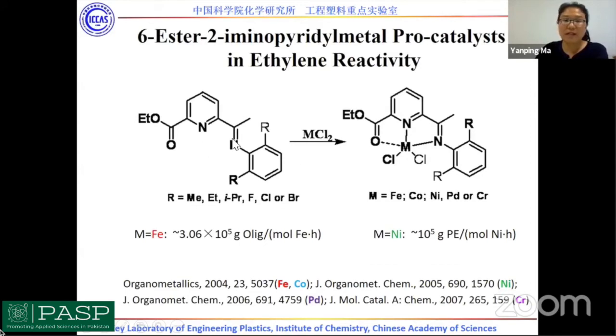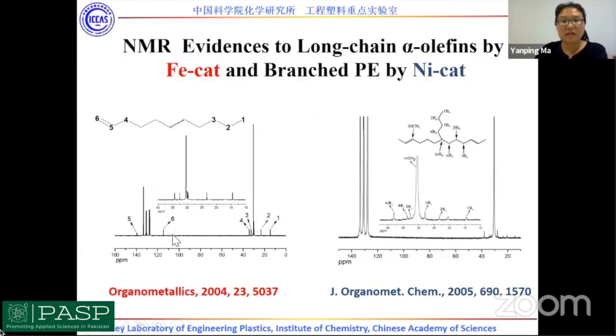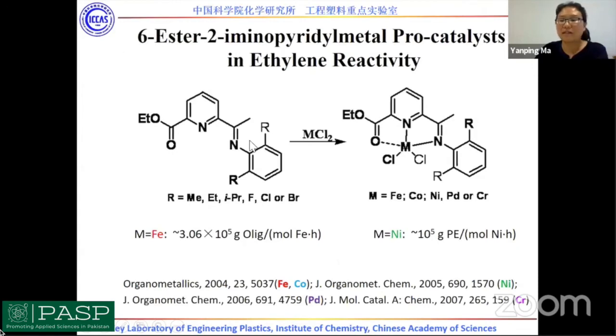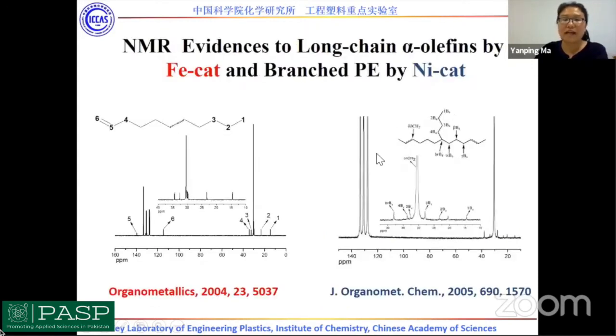This ligand is special. It can react with iron, cobalt, nickel, and palladium metal dichloride salt. It's interesting to find that if we use the iron catalyst, we get highly linear products. If we use the nickel catalyst, we get highly branched polyethylenes. It's interesting. Just by the same ligands, just the metal is different, we get totally different polyethylenes.